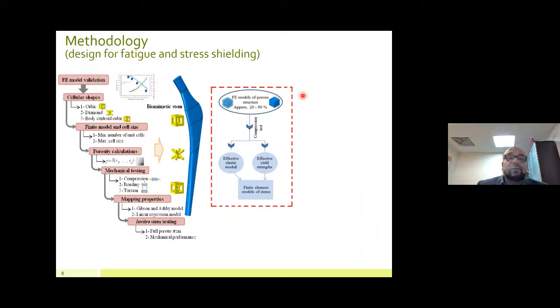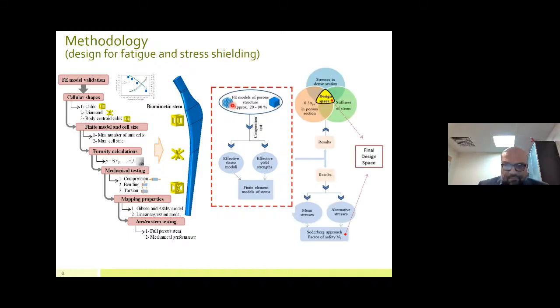So we basically played with different porosities of the microstructure. We had some compression tests to determine the elastic modulus and the yield strength, and then the best candidate gave us the full model of the stem. Once we achieved the full model of the stem, we proceeded in 2 aspects. It was reported in literature that cellular structures have a fatigue strength of about 0.3 of the yield strength.